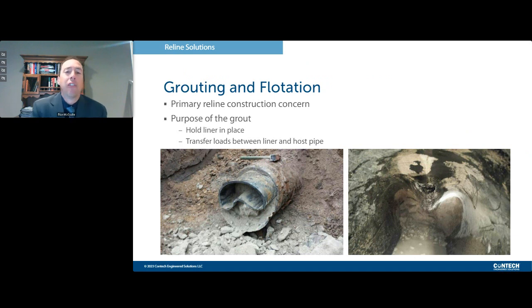Moving on to more of an installation related question, and that is grouting and flotation. We get a lot of questions about whether or not the void between the old pipe and the new pipe should be grouted, and the answer is unequivocally yes. The purpose of the grout is to hold the liner in place, but it's also there to transfer loads between the liner and the host pipe. So the trouble comes when you try to use pressure when you're grouting, and too much pressure can cause problems like you see in these pictures. And we clearly want to avoid those.